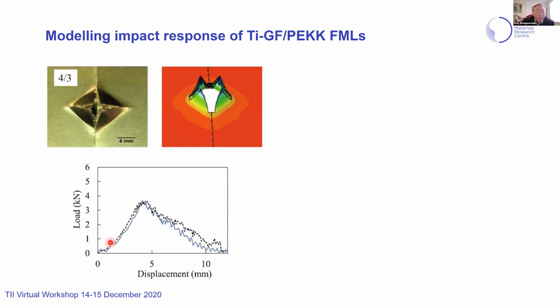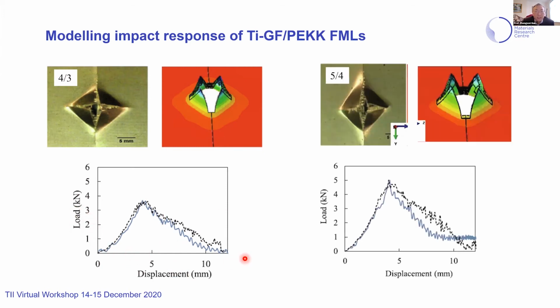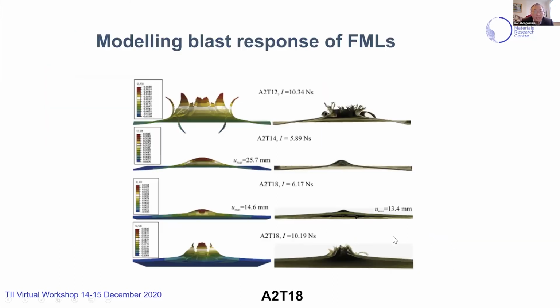So we have very good correlation between test and the modeling. The load displacement is also quite well simulated. So it's 5-4 and 4-3. Both have a good correlation in failure mode and also load against displacement. So failure mode is kind of a qualitative validation, and the load displacement is kind of a quantitative validation.